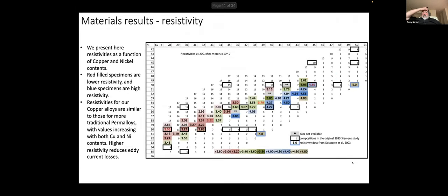First up, resistivity. The far left has the lowest resistivity values here, 2.86, as well as the lowest copper content. So copper is not a control on conductivity. It turns out that the closer you get to a 50-50 mix of these kinds of materials, the higher the resistivity is going to be.